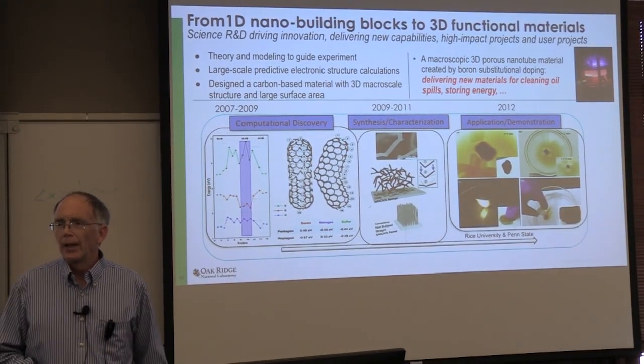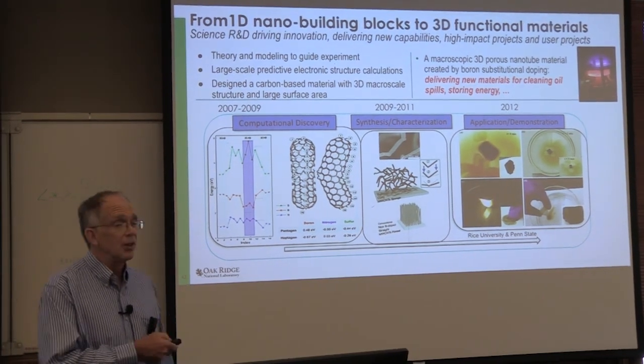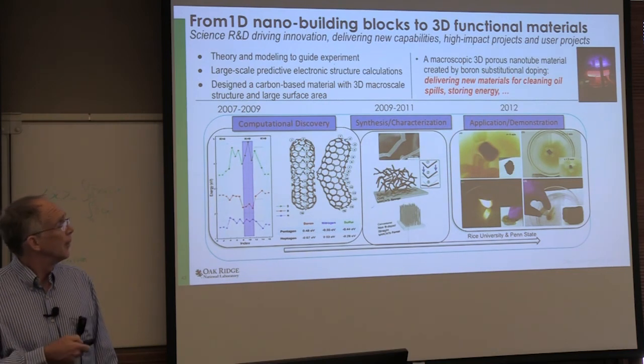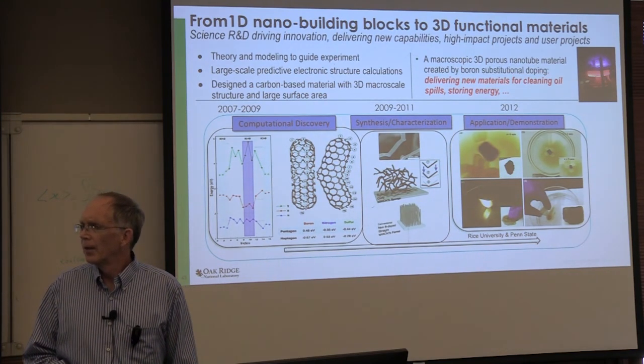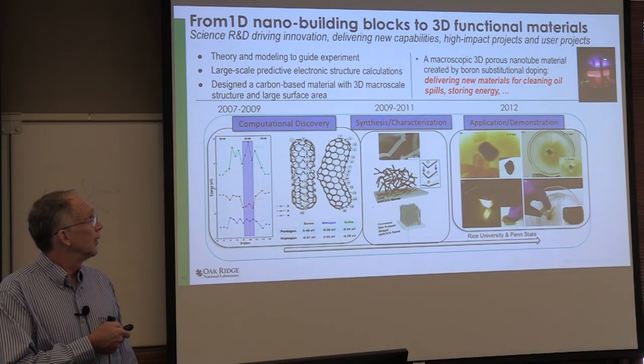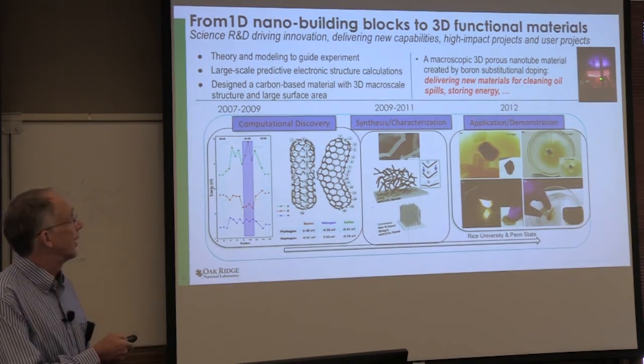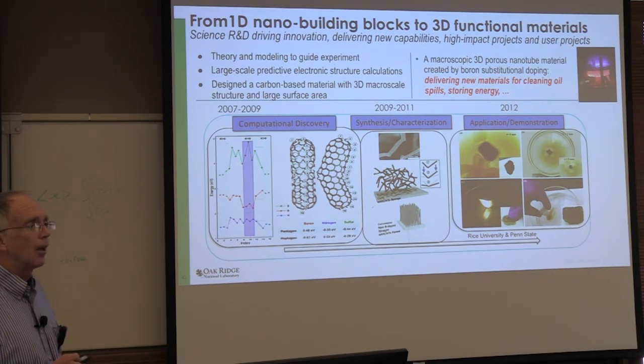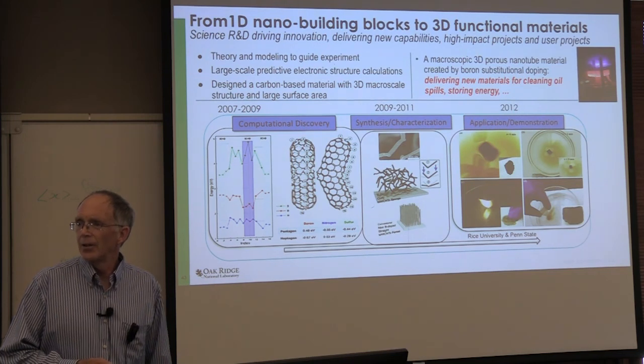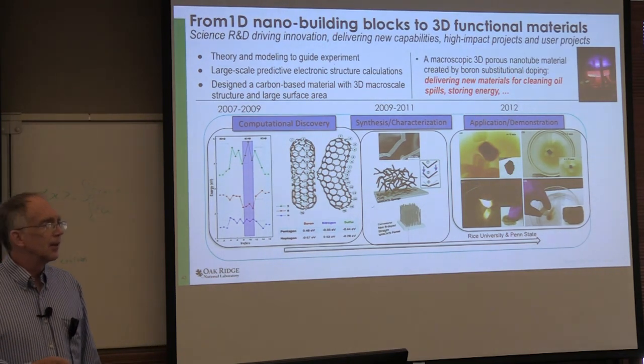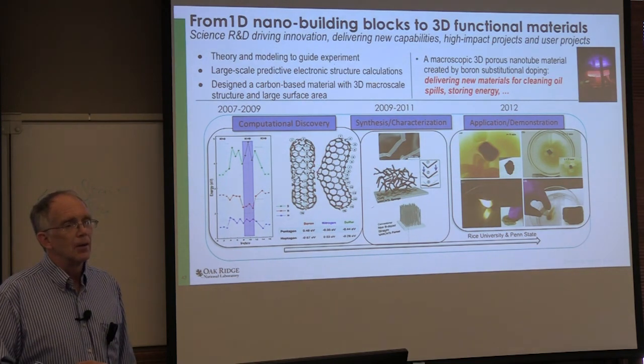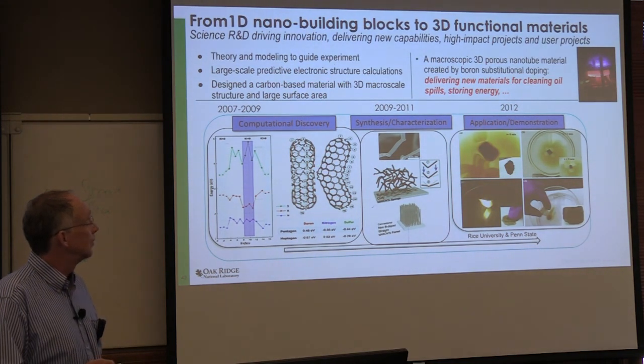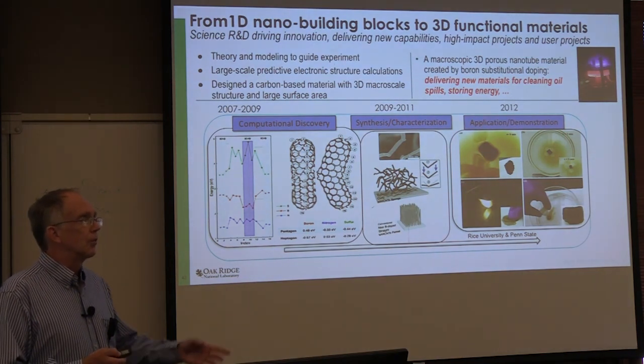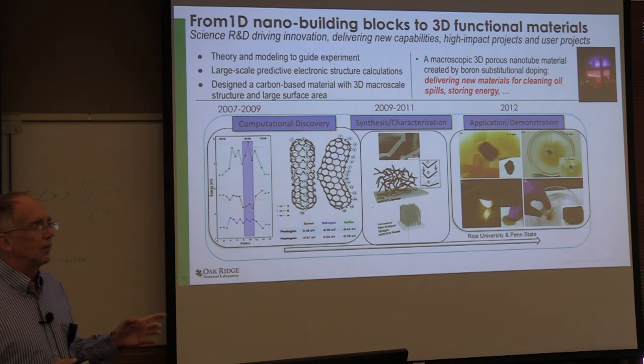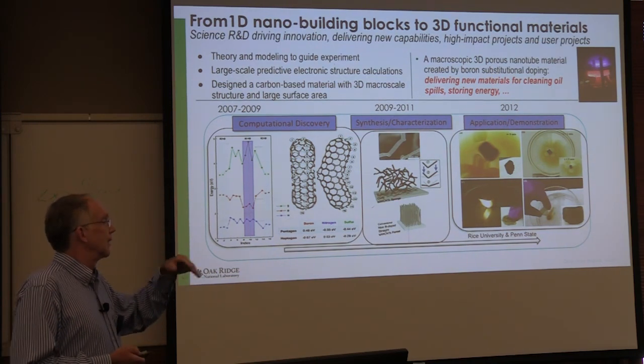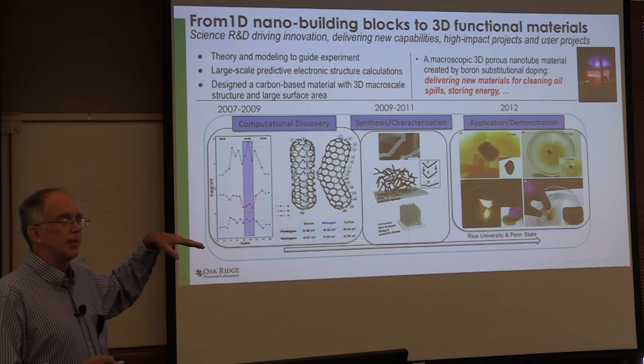So we asked the question, is there a way that we could promote the growth in a chemical vapor deposition chamber, and I told you a little bit about the plasma enhanced chamber, by using other elements than just carbon? Typically, it's a carbon precursor. You put in a vapor phase, and then it deposits on a catalyst, and you grow these tubes. So we said, what if we put other elements in there other than carbon, say nitrogen, boron, sulfur? Would they get substituted into the graphitic network of the carbon nanotubes? And if they get substituted in, what does it do to the structure and the growth? What we want it to do is make them longer, right? So we want something that can act like a surfactant and keep the thing from closing up and terminating.